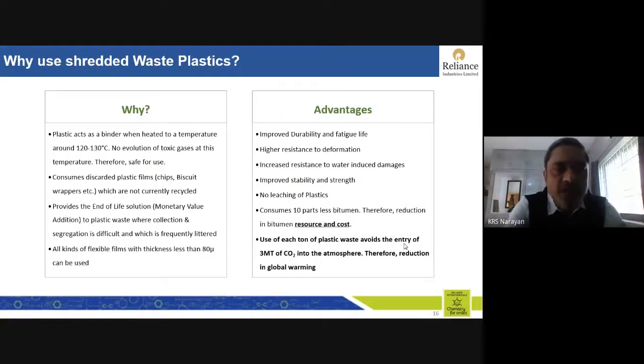Why should we use shredded waste plastic? Plastic acts as a very, very good binder. As I said, 120 to 130 degrees Celsius is the softening point. There's no evolution of toxic gases at this temperature. It consumes all types of multi-layered plastic, which are currently not recycled. So it provides an excellent end-of-life solution, an excellent solution to littering as well as landfill and incineration. And the challenge, however, lies in collection and segregation, as it is frequently littered.